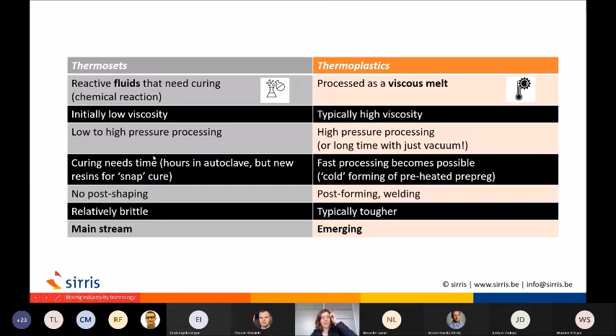Curing needs time. That is one of the main drawbacks of thermosets. Once it's impregnated, you still need time for the chemical reaction to go forward. But once the material is fixed, you cannot post-shape it, so that's a drawback. It's also relatively brittle, and these drawbacks lead to more interest in thermoplastic processing at the moment. It's more difficult to process, but the products in general have very nice opportunities that a thermoset composite doesn't have. And then I mainly talk about fast processing.